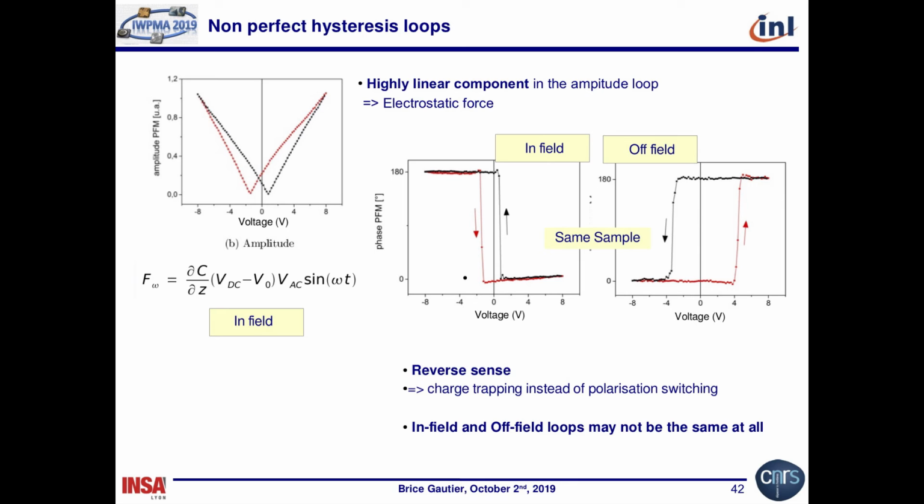You have a force acting on the surface which is exactly at the same frequency as the piezoelectric vibration, and the amplitude of the vibration due to this force is proportional to the voltage that we apply. This is exactly what you measure. This linear part there is the capacitive force acting on the tip. It is not the piezoelectric displacement of your lever.